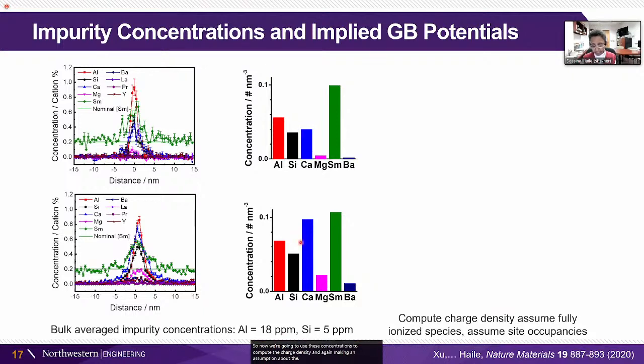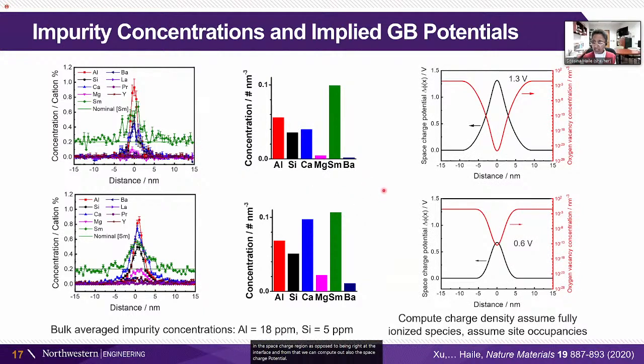So now we're going to use these concentrations to compute the charge density, again, making an assumption about the valence state of these impurity ions and an assumption that the oxygen vacancies, or the oxygen ions that provide the charge balance, are in the space charge region as opposed to being right at the interface. And from that, we can compute out also the space charge potential. And so this is the result that we get from these two interfaces. We see in one case a voltage of around 1.3 volts, and in the other, 0.6 volts. This one is lower largely because we have calcium, which is a substitutional dopant, which shields against these impurity concentrations, not because the impurity